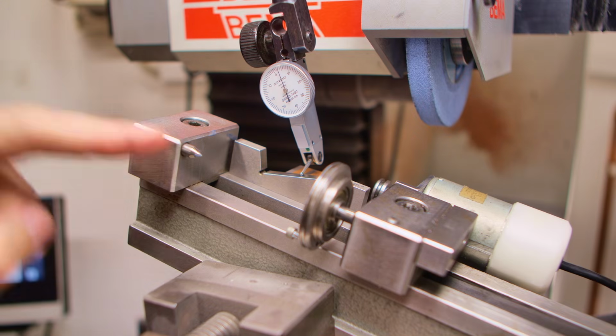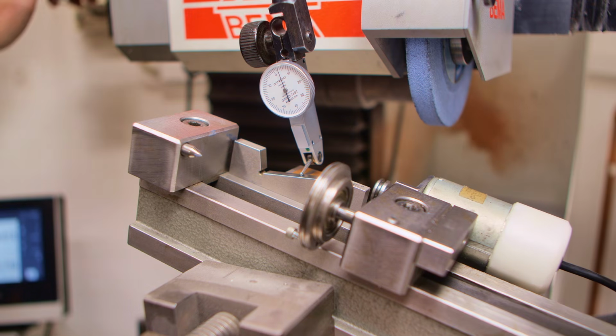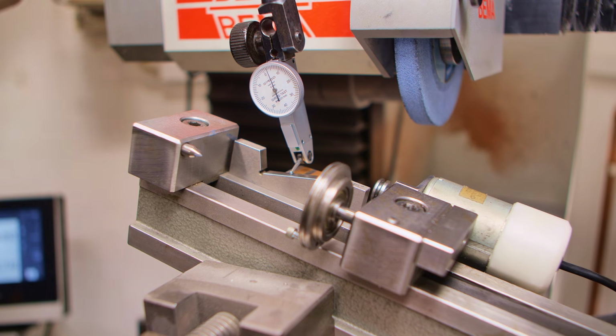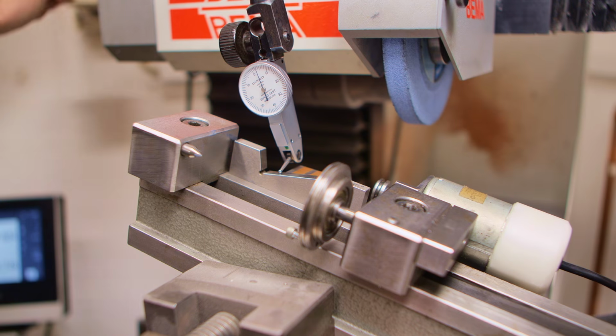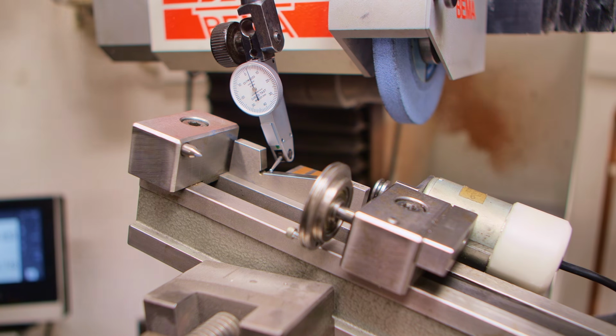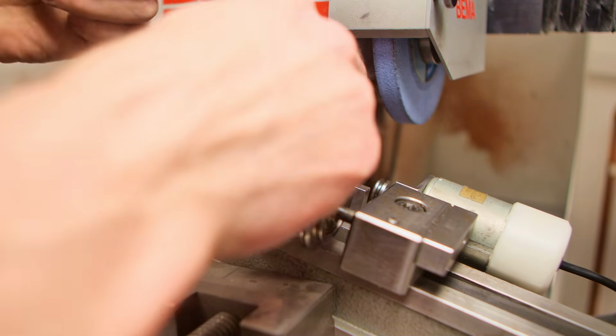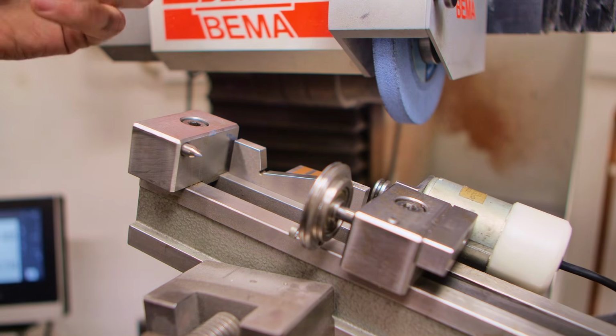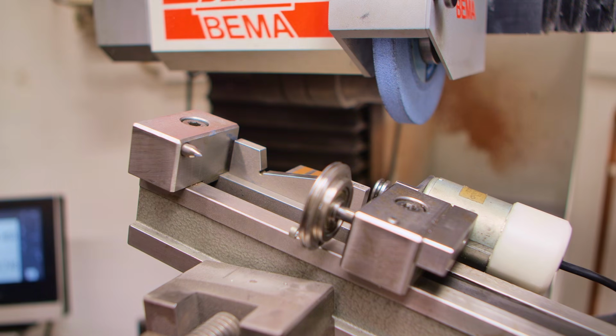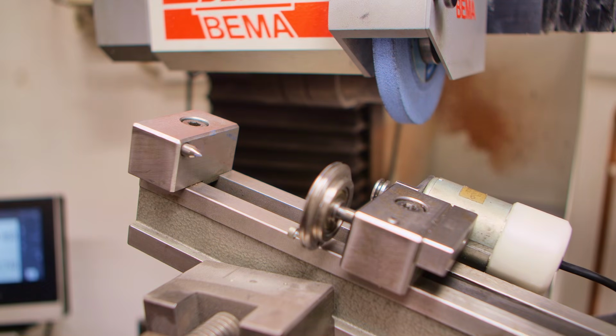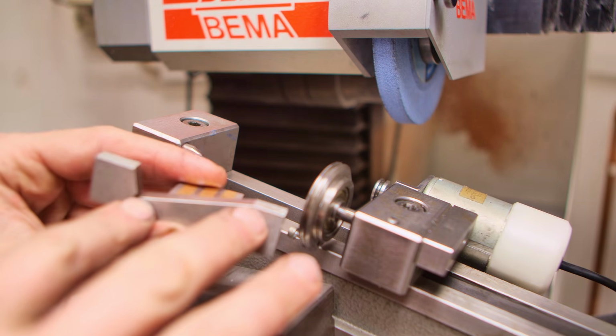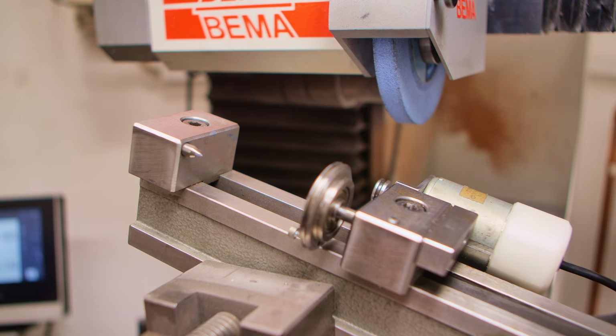I cocked the grinding fixture at 15 degrees with an angle block, and I indicated it in, just tapped it in with a hammer until I get a 0, 0 reading end to end on this angle block. I checked these angle blocks piece by piece against a sine bar, and they all are darn good for general shop work. And the taper we're grinding is relatively short, so indicating on such a long distance compared to the short taper we're grinding will make things better.